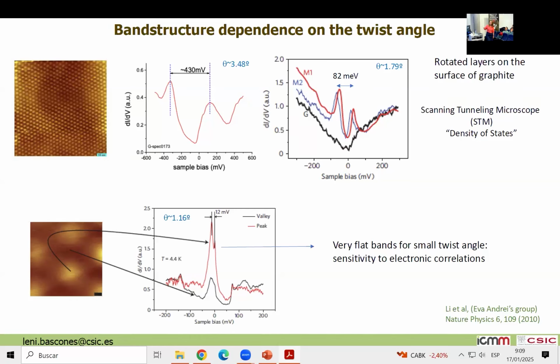And what she saw is that when she was changing the angle, this is the dI/dV, which is giving us the density of states effectively. You can see that these 2 peaks, which are van Hove singularities, where there is a lot of density of states, became closer and closer when the angle was made smaller. Interestingly, when the angle was around 1.1 degrees, more or less 1.16, they were really, really close, about 12 millielectron volts from each other.